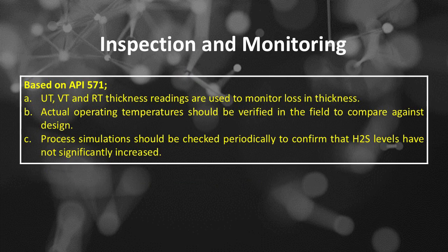High-temperature hydrogen (H2) and hydrogen sulfide (H₂S) corrosion inspection and monitoring based on API 571. Number A, UT, VT and RT thickness readings are used to monitor loss in thickness. Number B, actual operating temperatures should be verified in the field to compare against design. Number C, process simulations should be checked periodically to confirm that H₂S levels have not significantly increased.